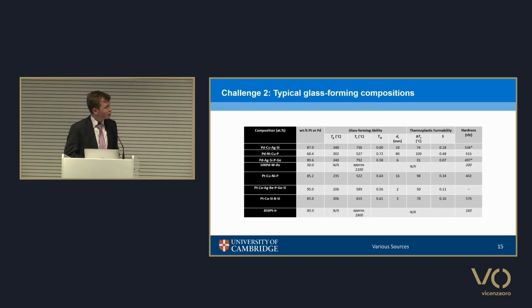So I show a table, which is perhaps some of the figures you may have already seen, but you'll see that as we go to our higher finenesses in our platinum and palladium systems, we typically have an issue with critical casting diameters dropping off markedly. And these ultimately mean that they're of little commercial use at the moment. And we'll also see a drop in this thermoplastic formability, characterized by this S value here, and that's of importance for the injection molding analogs.